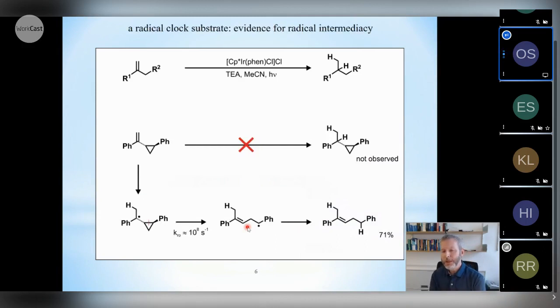And one of the first mechanistic experiments that Miriam did, along with a postdoc from China, Xingwei Guo, is this radical clock experiment, where they observed that this starting material converts to this ring-opening rearrangement product. And that really strongly signals that there might be a radical intermediate of this type here, a tertiary carbon-centered radical that would be formed somehow along the way.